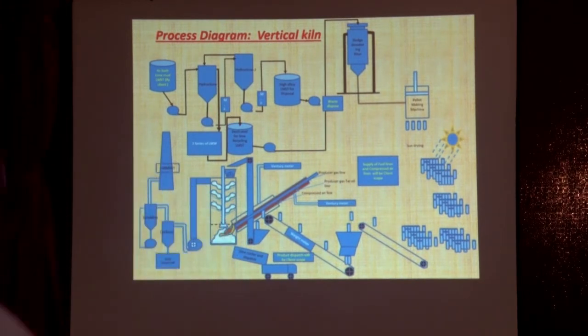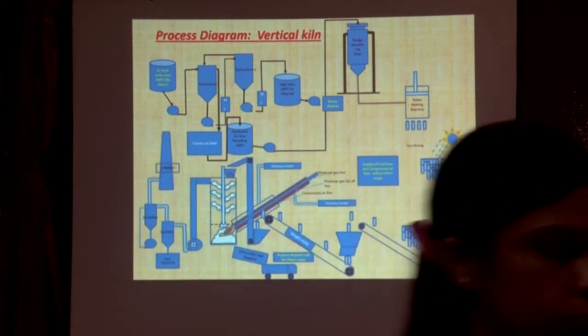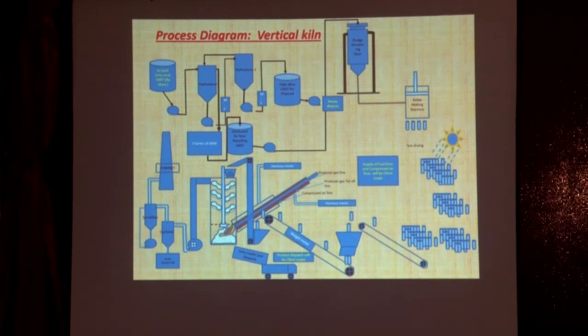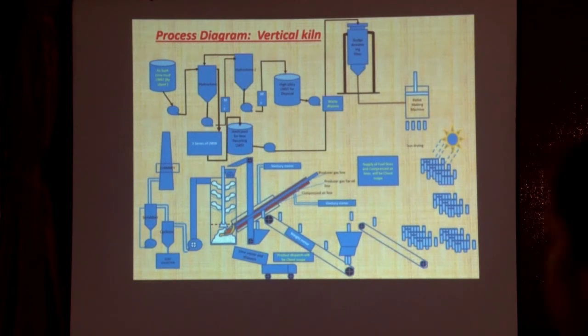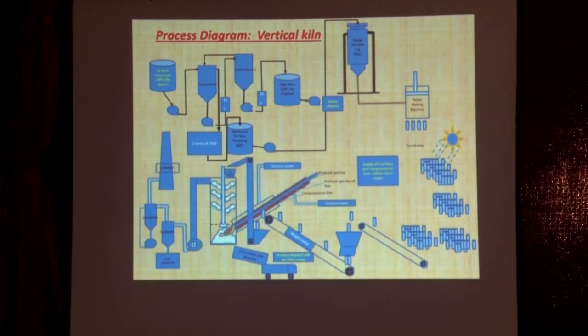From the mud washer, we collect this lime sludge and compress it in the lime sludge hydraulic pelleting machine. We developed that machine and supplied it to a paper mill for that lime sludge, and the pellets made were as hard as limestone. It is not limestone, but it was equivalent to limestone. It has enough hardness and compactness, and its dryness was approximately 65% on average.